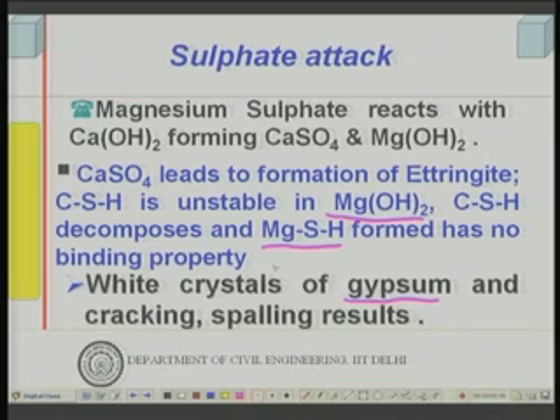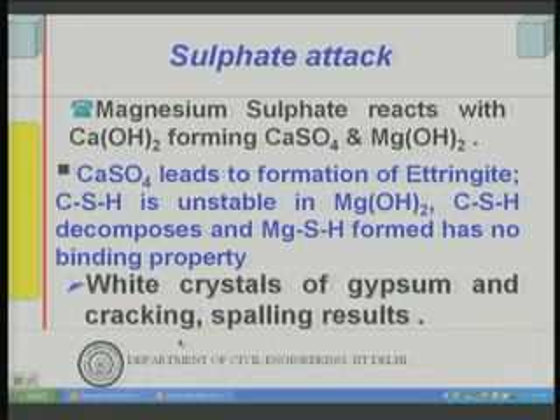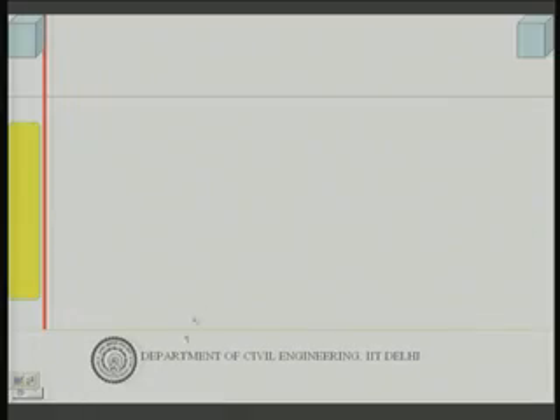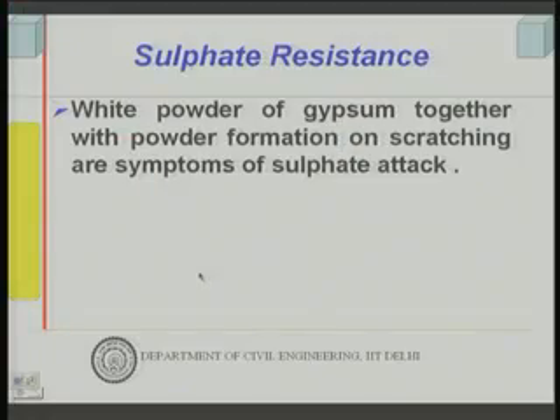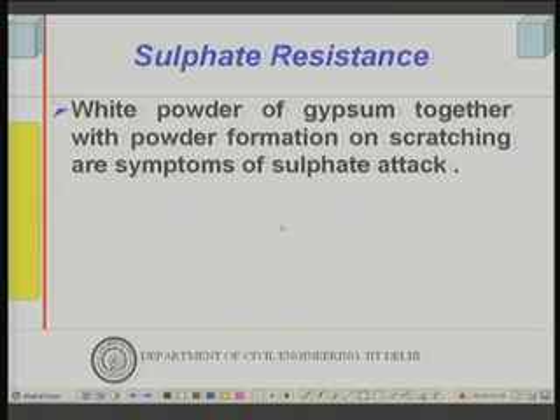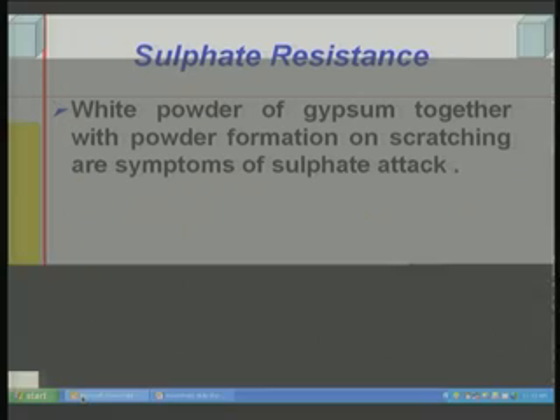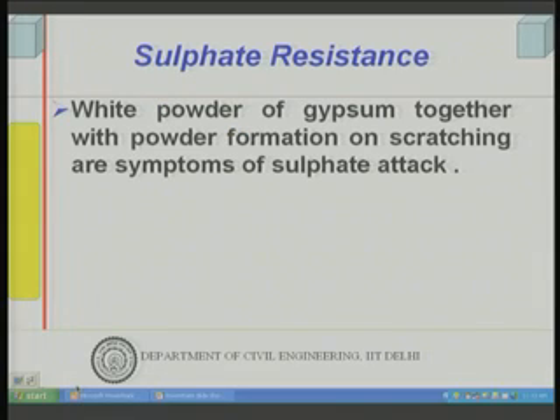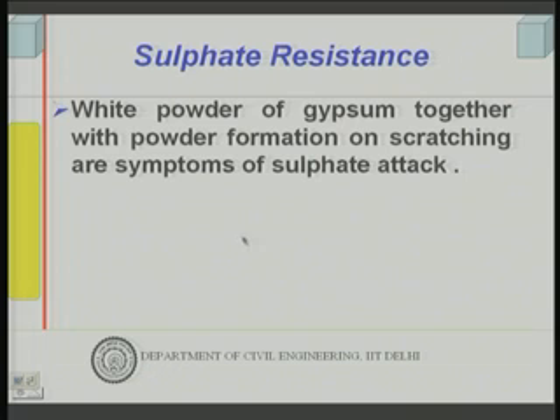Now, what are the symptoms? You actually see white crystals of gypsum when such sulphate attack takes place, and you will obviously have cracking, spalling, etc. So, sulphate attack finally results in cracking and spalling of concrete, and there is formation of gypsum powder. So, you will see white gypsum crystalline powder. If you scratch the surface, for example a column's vertical concrete surface, you will find a lot of material comes out, dust and fine powders. And then white crystals of calcium hydroxide are usually present. So, this is the symptom of sulphate attack.